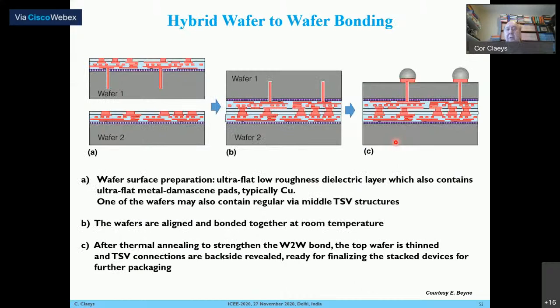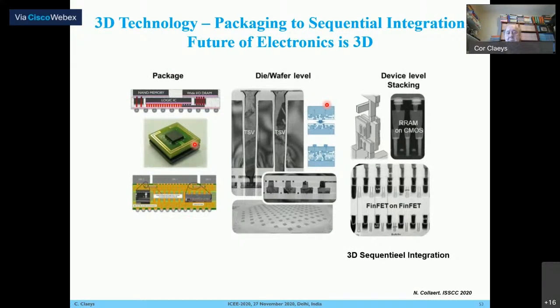Another approach is what is called hybrid wafer-to-wafer bonding. Again, you start with two wafers with different functionality, but now in one wafer, you already have through silicon vias fabricated. Then you do again the room temperature wafer bonding, a temperature step to improve the bonding strength, wafer thinning, and then finalizing the packaging. So that means you can come to a higher functionality for the same area. You can use system in package. You can do wafer level bonding or die to wafer bonding. Both can be used. But there is also a third approach, which is called device level stacking.